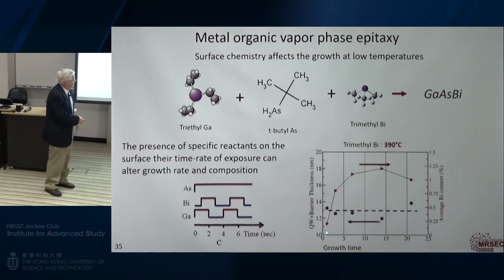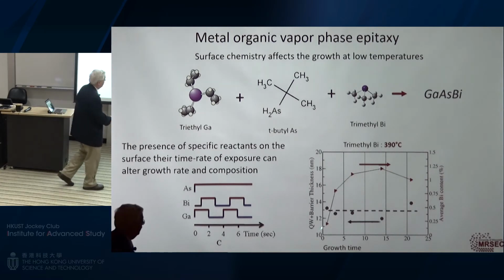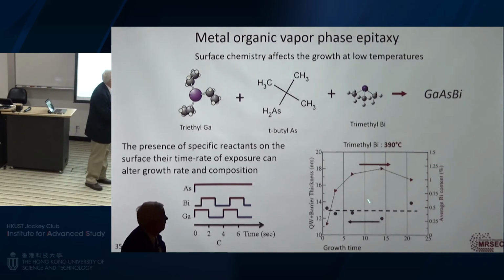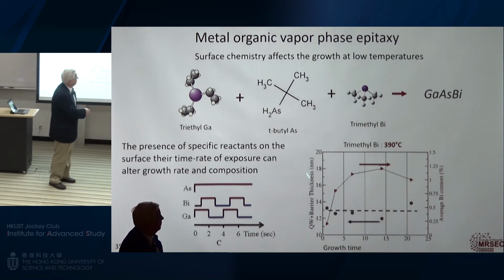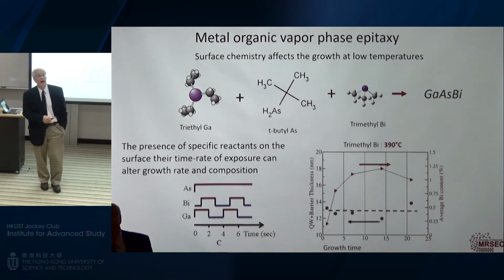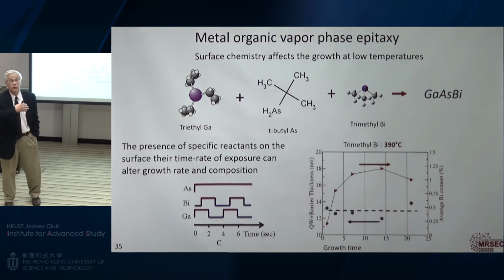And as I'm growing, so this is growth time, I start the reaction and it's growing the film, depositing and depositing. What happens is after a very short period of time, even though I have a flux of reactants into the system, it doesn't grow anymore. It stops growing. So it's going into the system, but it's not growing.